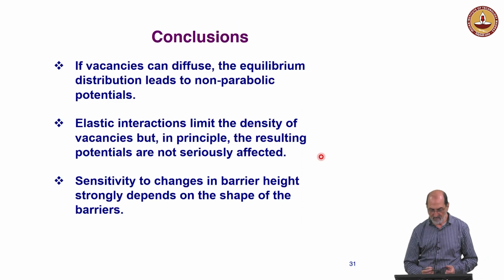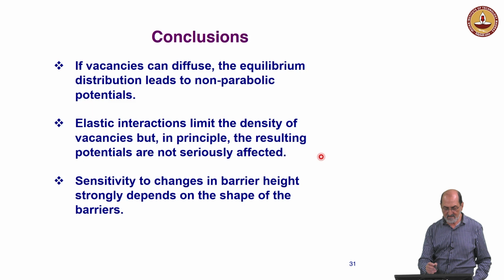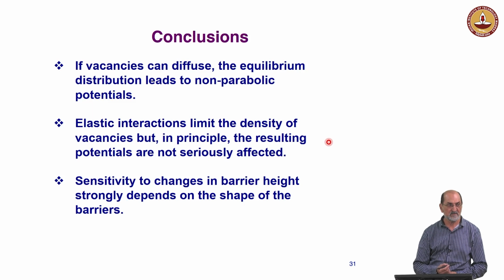Okay, then conclusions. If vacancies can diffuse, the equilibrium distribution leads to non-parabolic potentials. We have included elastic interactions to limit the density of vacancies, but in principle the resulting potentials are not seriously affected.